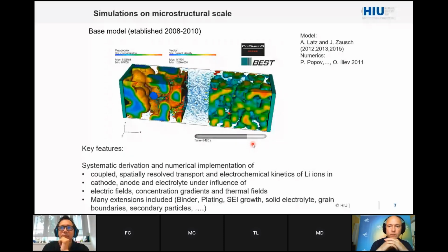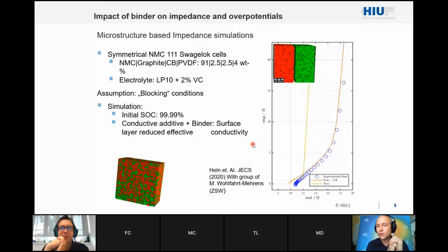So I wanted to start with the binder, and actually it's a nice coincidence that the first talk was on binder migration and inhomogeneities due to the production in this topic. This is work in collaboration with Marco Wolfram-Behrens. He talked yesterday also on thick electrodes, where we are collaborating a lot. So what they did were impedance spectroscopy measurements on NMC in a symmetric fashion. This means both are fully charged, so it should be a blocking configuration.